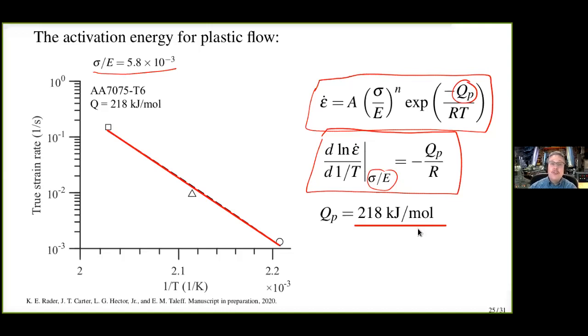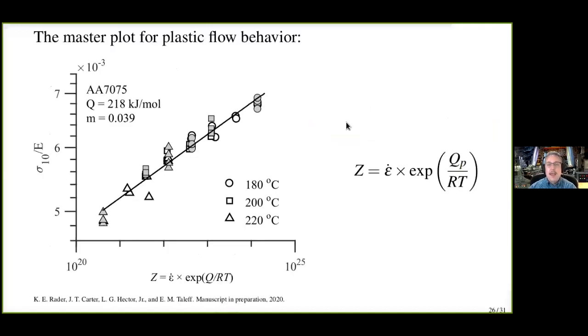So again, interesting science to explore, but from a practical point of view, we can take that activation energy and we can use the Zener-Hollomon parameter here. And as we previously normalized time by an activation energy to give us basically a reduced time, we can now normalize strain rate with this activation energy function of temperature.